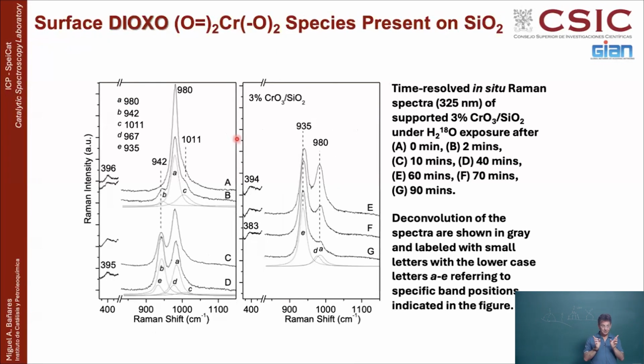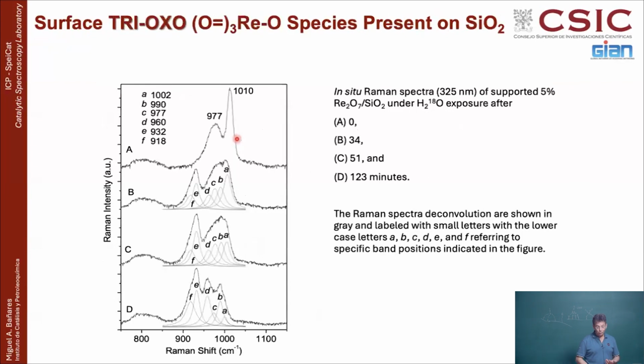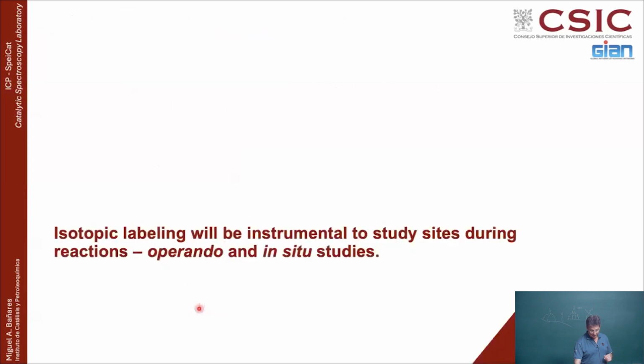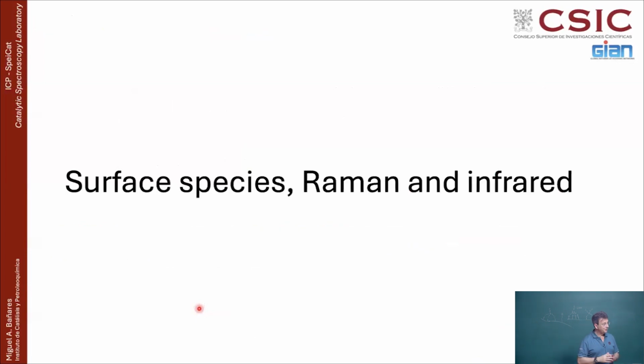Chromium is a dioxo species. Then things are not so clean and one is not replaced by the other, because then you can get both of them, like 16-16, 16-18, 18-18. So you have a plethora of peaks and things can get more complex. This is already telling you, okay, this is a dioxo species. And if you do that with rhenium, you get crazy, because you have all these very many possibilities of 1, 2, or 3 of the oxo groups replaced by oxygen-18. So you begin from something which is very nice to something that is a very good headache. But this is telling you that this is a trioxo if you make a detailed analysis of the system. And isotopic labeling can also give you a lot of information during operando reactions, but that will be in future chapters, not today.